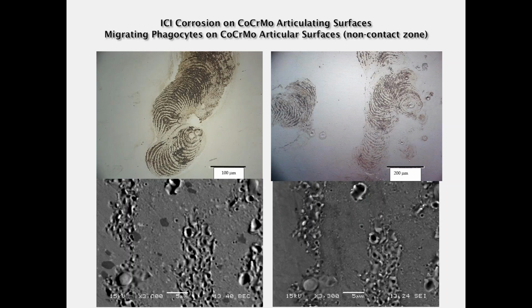What we think is the consequence of those biochemical species that are generated by inflammatory cells is direct attack of the implant alloy surface. And we began to see in implant retrievals characteristic appearance of cell-like processes on cobalt chromium molybdenum alloy surfaces, which demonstrated corrosion attack of that surface. So these are migrating phagocytic cells, and the dark concentric rings are these regions where you see a ruffled border-like appearance of corrosion damage of the alloy itself. This is not a deposition on the surface, but this corroded region is lower than this uncorroded region out here.